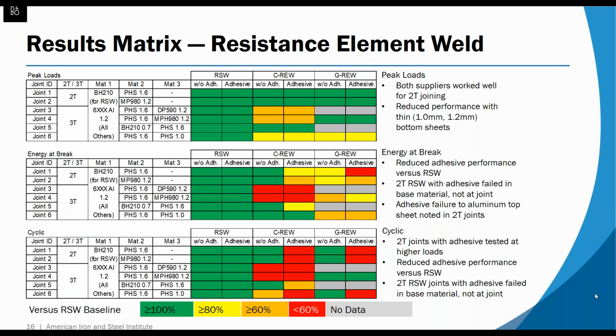In cyclic fatigue, generally speaking, on the two-thickness without adhesive, they were competitive. In the three-thickness, we had the same difficulty as with peak load and energy, in that the smaller nuggets in the bottom sheet of thinner material did see some degradation in the cyclic loading.